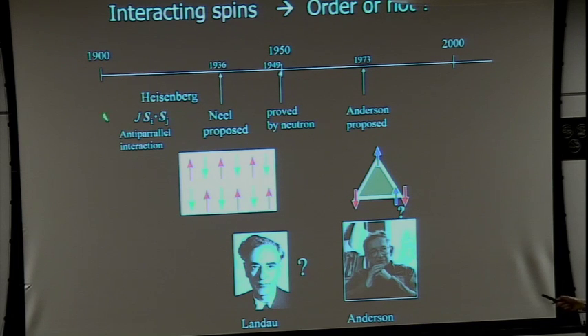The Heisenberg interaction, with spins located on a square lattice, gives a Néel state. But interestingly, Landau was very suspicious about the realization of the Néel state, because spin 1/2 should exhibit quantum fluctuations. However, neutron experiments proved that the Néel state is the real ground state. So Landau's opinion was wrong.